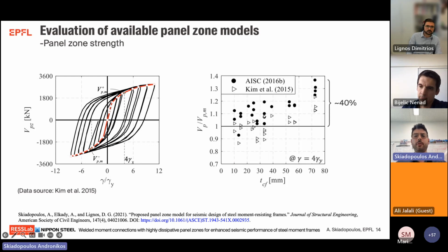Regarding the panel zone shear strength at 4 gamma Y, again from the collection of data that I described before, we deduce the panel zone shear strength at 4 gamma Y, which is the limit in the American code. And typical panel zone models are similar in nature to that of the American code. As also described before, these tend to overpredict the panel zone shear strength by more than 40%, especially when thick column flanges are utilized in the design. It should be noted here that Eurocode does an even worse job in predicting the panel zone shear strength, but this is not shown here for brevity.